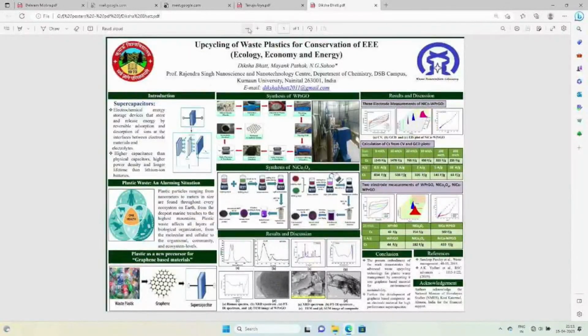Which are waste plastic and energy crisis. So we find a common way to resolve these two issues by converting waste plastic into reduced graphene oxide via a two-step pyrolysis method and use that material as an electrode material for the supercapacitor, which is an energy storage device. Here is the schematic representation for the synthesis of reduced graphene oxide from waste plastic. In this synthetic process, first we collect waste plastic from the local region of Kumaon, and then after cutting, washing and drying, we place it in a catalyst chamber where we mix catalyst in a fixed ratio and then place it in a tube furnace for the first pyrolysis.